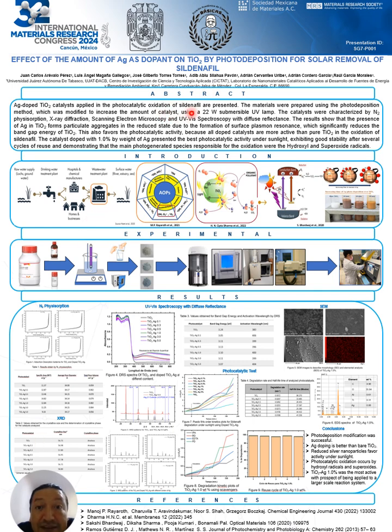Unfortunately, this process using titanium dioxide is only activated under UV light. But this disadvantage has been overcome by doping metallic or non-metallic ions on the surface of the titanium dioxide. This reduces the electron-hole recombination and improves the spectral response.